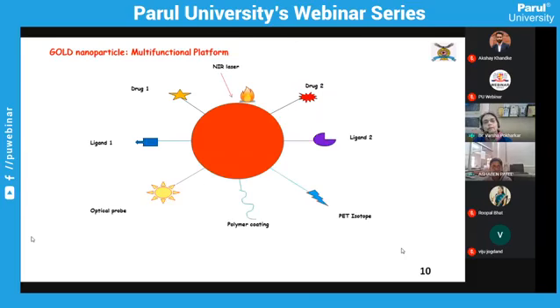Gold nanoparticles are of great interest because we can decorate the particle surface with whatever we want. We can put different drug molecules on the surface, we can attach different ligands of different types, and we can go for a coating on the surface, any kind of polymer coating, for example a PEG coating, polyethylene glycol coating. We can attach an optical probe, or we can attach a PET isotope. This is particularly for imaging or diagnostic purposes.